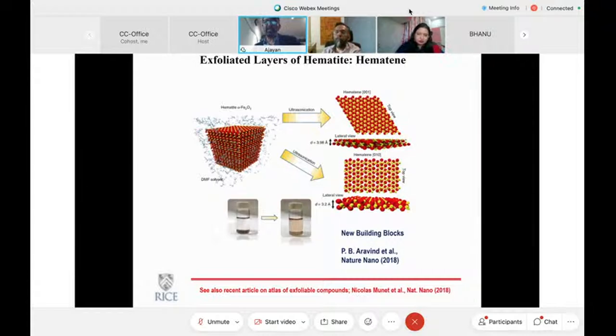So it's really an interesting approach, because you can now get very, very thin layers of even traditionally non-layered systems. And the point for this particular material is that when you make such thin layers, going to less than a nanometer or so, you start to see some new properties emerge. For example, when this iron oxide was very thin, we found that it starts becoming ferromagnetic. Normally, iron ore Fe2O3 is not ferromagnetic. So there are some emergent properties that appear when structures become very thin. That's another reason why one should study these materials.